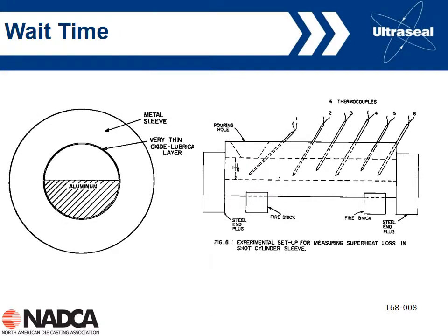So why should longer wait times hurt? You kind of think intuitively longer wait times would help by reducing the turbulence from the pouring. Here again we've got data, from the transactions all the way back to '68. They used thermocouples to measure the temperature of the metal in the shot sleeve. We're looking end on in the shot sleeve here, from the side, and you can see they've got 5 or 6 thermocouples coming in, and they measured the temperature as the metal sat in the shot sleeve.